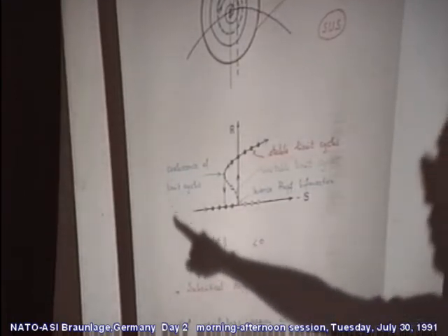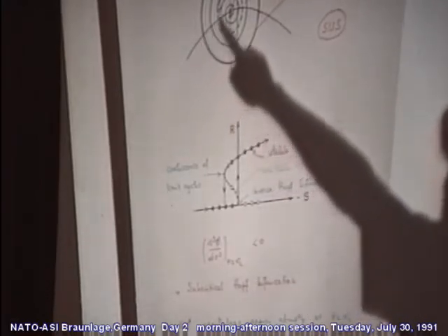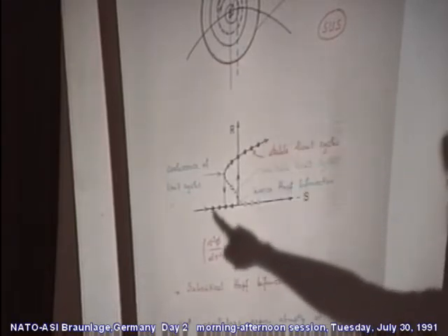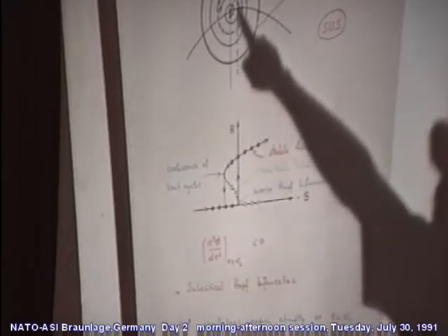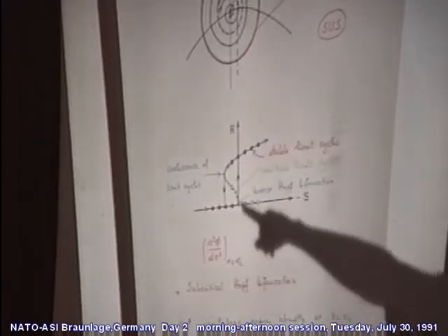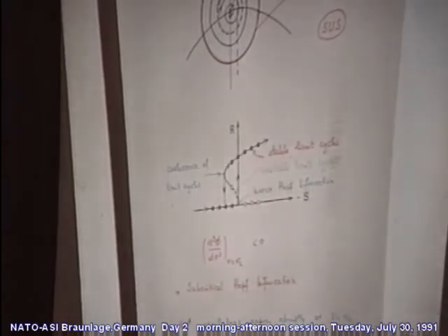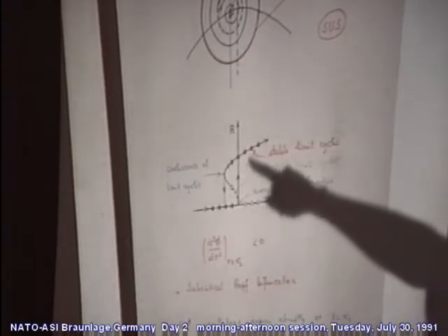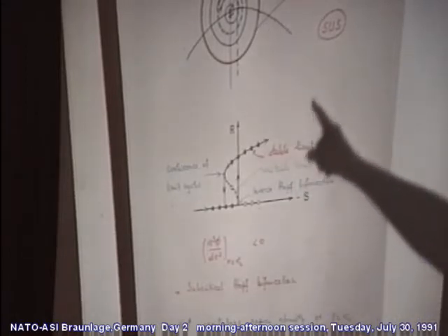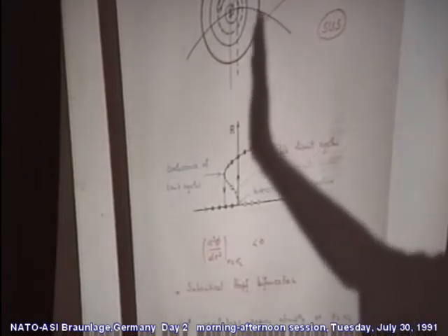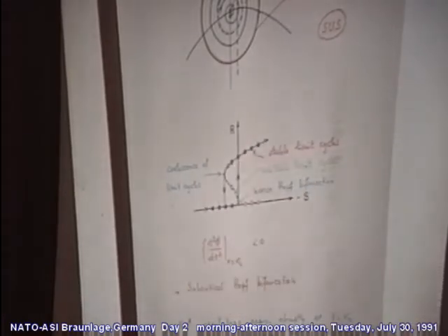And what would you follow when S increases, that is, when the slope increases and then decreases? You follow this stable point here, until you are at the top of the curve. At this point, you have immediately oscillation with a large amplitude, which increases when the slope decreases. And when you return, that is decreasing the imposed velocity, you have a hysteresis, you go toward this point and you jump to the stable motion.